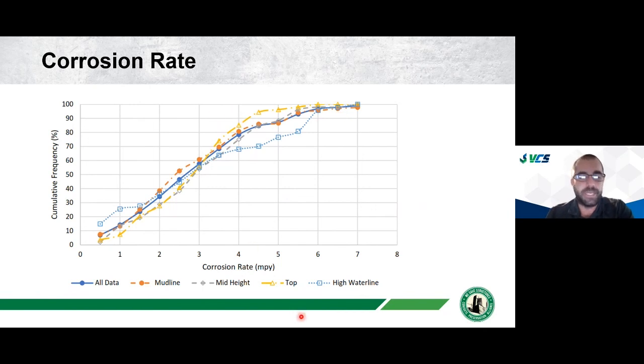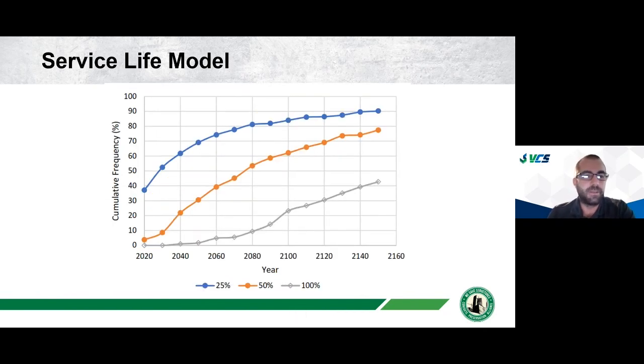And then we can also take it and project out a service life. If we have a certain corrosion rate per year and we know the thickness of those walls, we can project out how much of the wall will have 25% section loss, how much will have 50% section loss, and how much will have 100% section loss over time. The survey was done in 2020. Right now, about 40% of the wall had a 25% section loss, and that percentage is going to grow over time. And we can see different years.